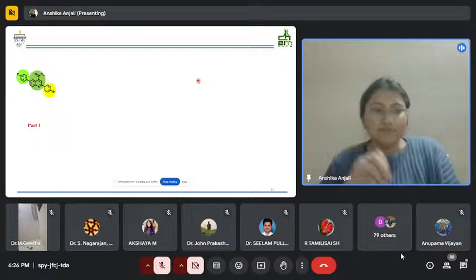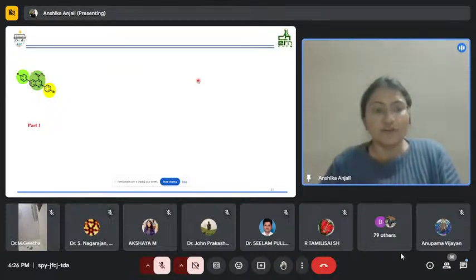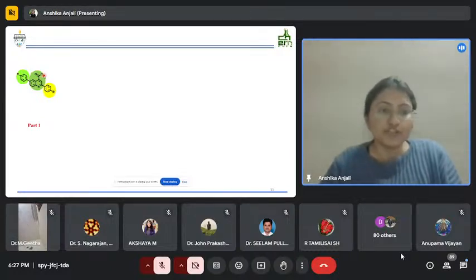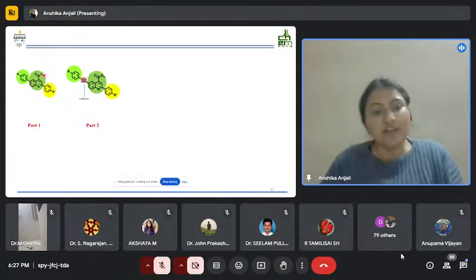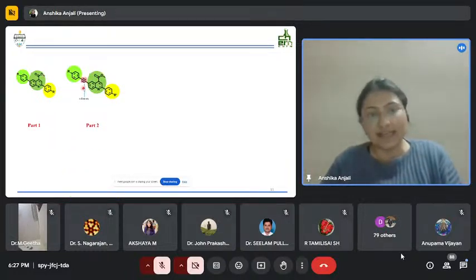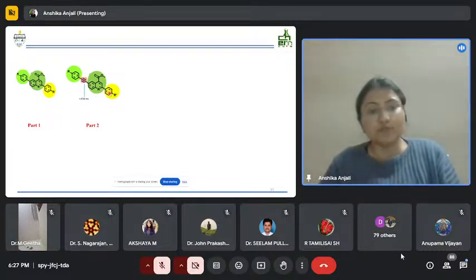So during my PhD work, I worked on this quinoline-based molecule, and in the first part of the work, we have taken 4-carboxylate quinoline as our core moiety. Then at the ends, we have a substituted phenyl group as our pi end caps. So here we have introduced 4-carboxylate. We have introduced this ester group at the fourth position to improve the overall solubility of the compounds. In the later part, we have introduced ethynyl as a pi-conjugated spacer, which was supposed to give rigidity to the whole compound and assist in self-assembly.